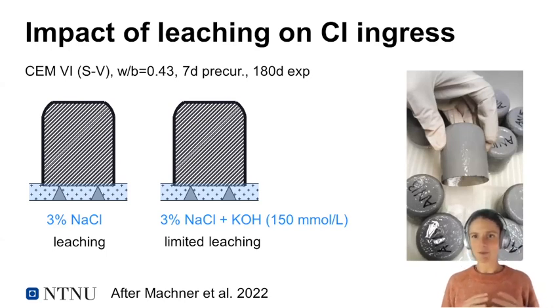And we exposed mortar samples with a novel cement, which was developed in this project, to two different exposure solutions. So on the left, we have 3% sodium chloride. And then we had the other exposure solution where we added potassium hydroxide. We added 150 millimole per liter to simulate a little bit the alkalinity level of the pore solution.